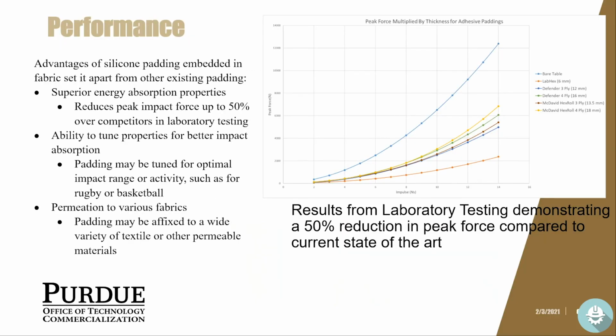The advantages of silicone padding embedded in fabric set it apart from other existing paddings. Our padding has superior energy absorption properties, which means in one layer it can reduce peak impact force by up to 50% above 3 or 4 layers of competitors in laboratory testing. The ability to tune properties for better impact absorption means that the padding may be tuned for the optimal impact range of the activity, meaning a different padding may be used in rugby, football, basketball, or other sports. The permeation of our padding to various fabrics means that it may be affixed to a wide variety of pre-existing textile or permeable materials. On the right is the graph demonstrating this peak force reduction.